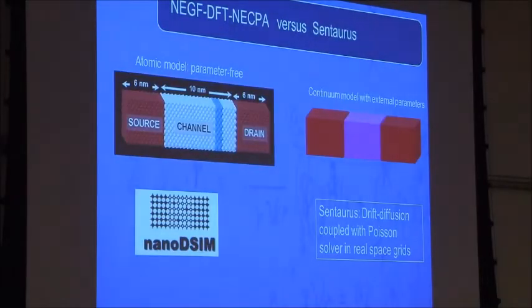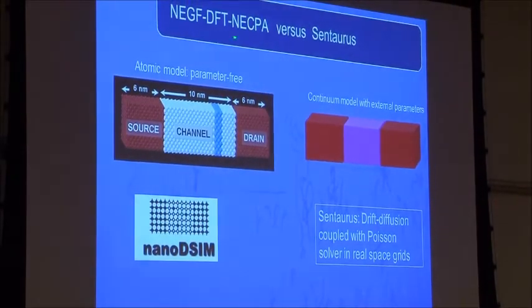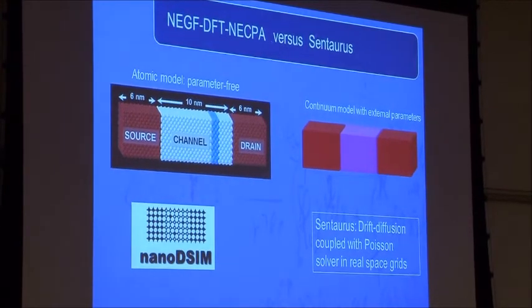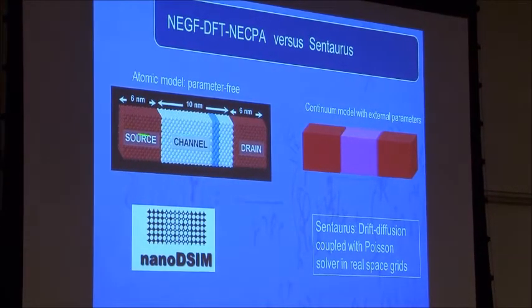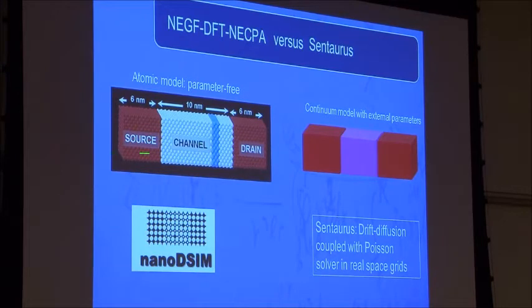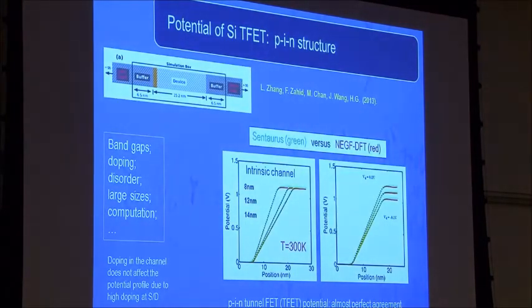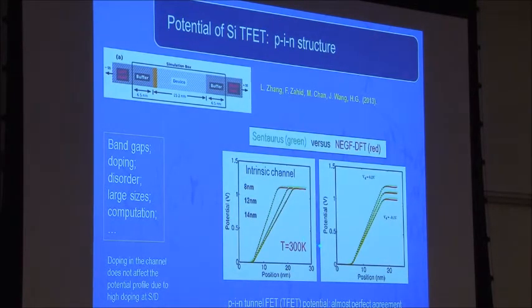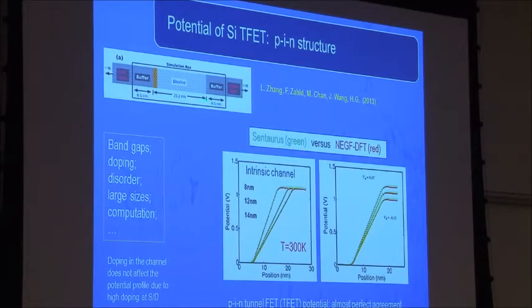What we do is use our tool, with everything from first principles and no parameters. We do a 6, 10, 6 nanometer silicon channel with this atomic self-consistent method, and then we use Sentaurus to do the same. So we did a TFET. This is the potential. We calculate the potential at equilibrium and at non-equilibrium, at 300 Kelvin, for a silicon PIN structure.